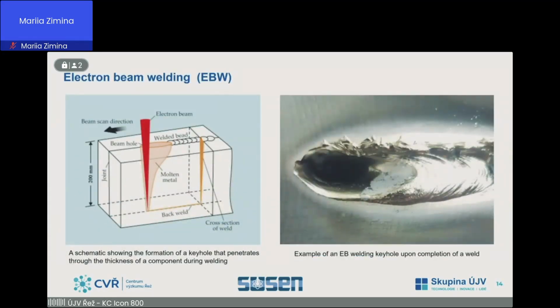The process employs a beam of high-energy electrons between two workpieces that are closely fit together and in contact with one another to join the materials. The electron beam causes the material on either side of the joint to melt, and the resultant vapor pressure of gaseous metal generates a keyhole through the full thickness of the joint. The keyhole is advanced along the joint seam as the weld is being performed and closes just behind the weld front, as shown in the figure.